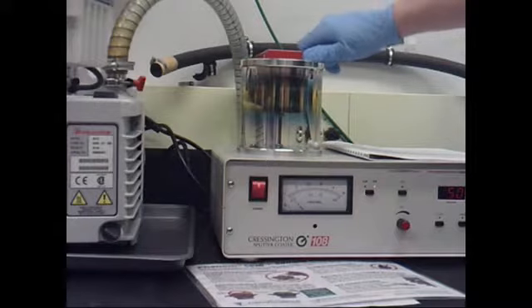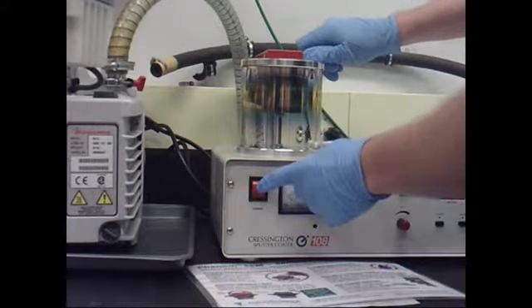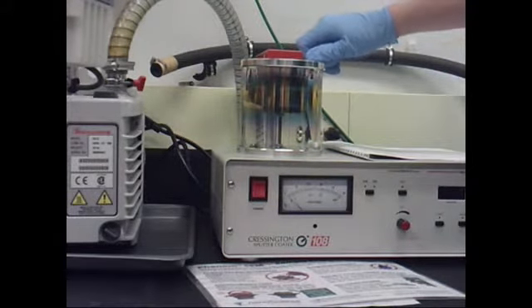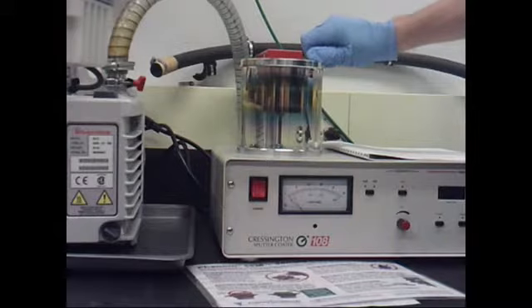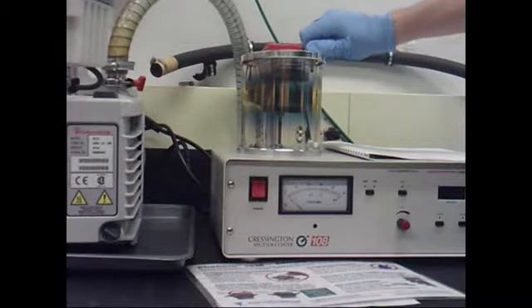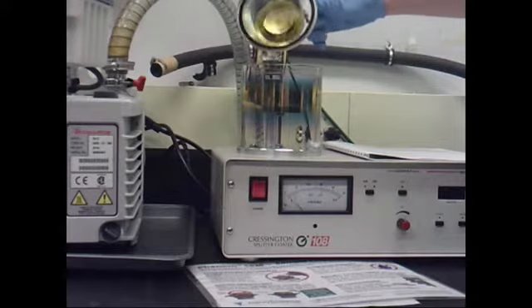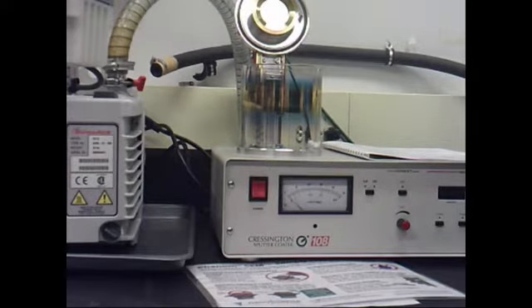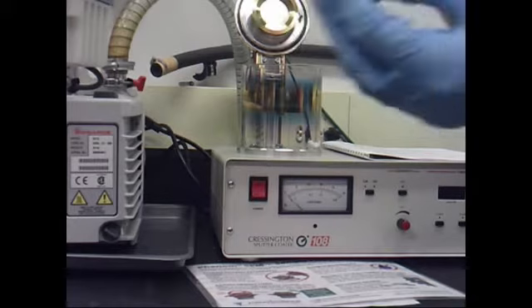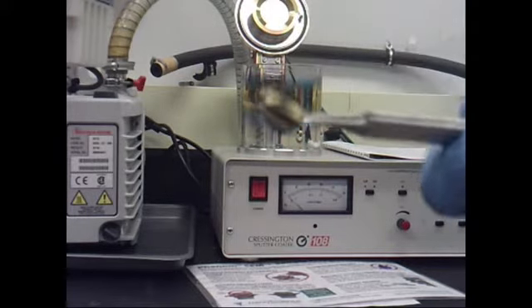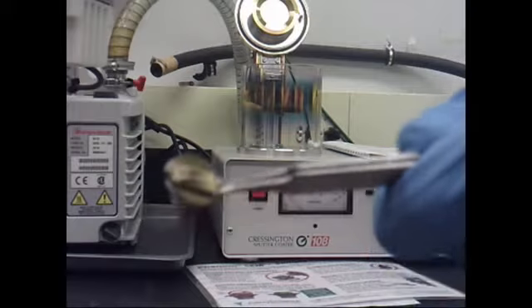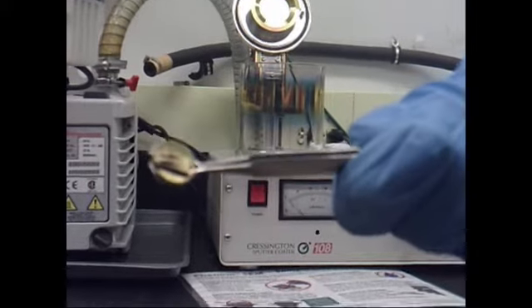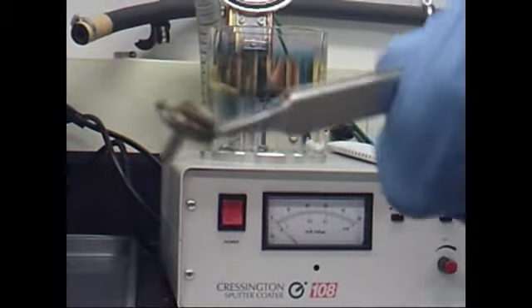You will start to hear gas flow back into the chamber. Also, for good measure, go ahead and turn off the chamber. Once the chamber is completely vented, you should be able to lightly pull up on the chamber, and your sample is successfully coated. As you can see, our sample went from being an orange color to being a metallic gold color. This is the result of an atomically thin layer of gold being present on our sample, which now makes it conductive and perfect for SEM imaging or some sort of EDS style analysis.